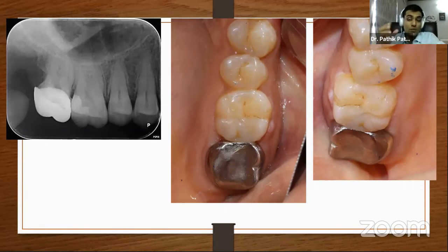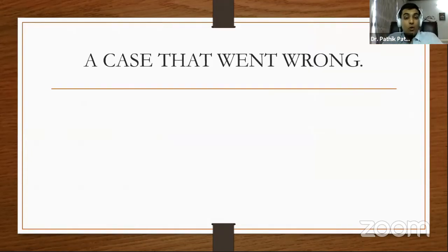And then because the light should reach at great depths for the direct composites to cure, that's why we are not using direct composites generally to lute any of the indirect restorations or even posts in the post endodontic restoration. Now I am going to show you one of my cases which went wrong at the last step. You would be surprised to see it is such a good case, but when you take the post-operative x-ray, you know where you have missed out.